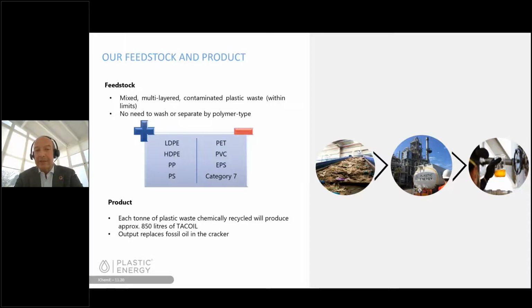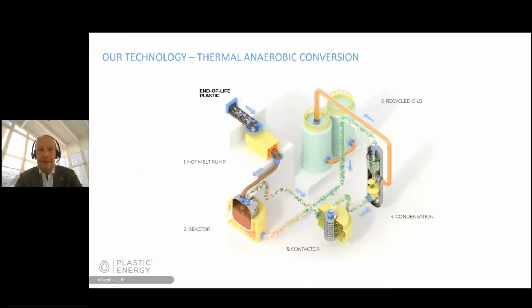There is a right size of this type of chemical recycling plant in order to make economic sense. We are talking something in the range of over 15,000–20,000 tons of plastics to be processed per year, and that will have a conversion yield of, for every 1 ton of plastic coming into our process, about 850 liters of TAC oil, which is the brand name of the oil that we produce, that stands for thermal anaerobic conversion oil. This TAC oil is sent later on to the cracker and blended with the naphtha feedstock.